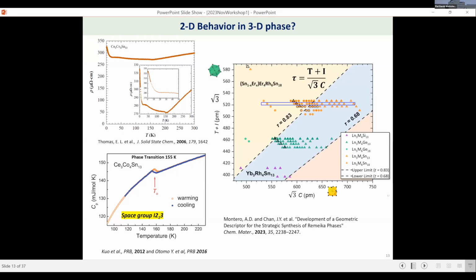And so one of the things that we did, because we were doing data mining, one of our joys is, can we predict? Instead of making every 3, 4, 13 compound known to mankind, these Remeika intermetallic perovskite phases, one of my graduate students decided to think about the geometric descriptors that would be critical to predicting whether a cerium compound or a ytterbium compound, pick your favorite lanthanide, can we predict which crystal structure type? It turns out that the Remeika phases, there are quite a few of them. There's the one that I just showed you, but there's this other one with a funny formula.